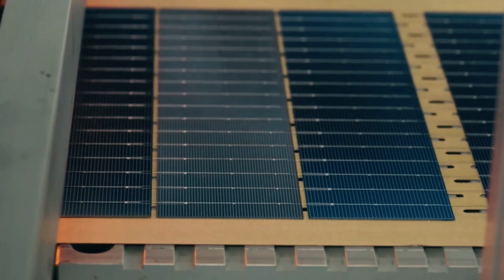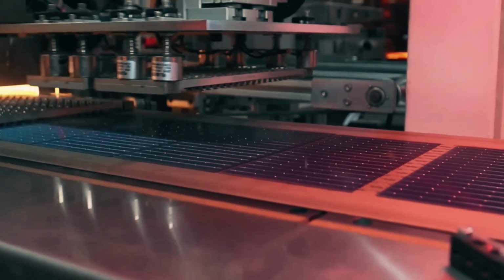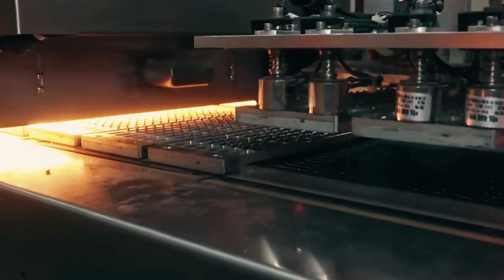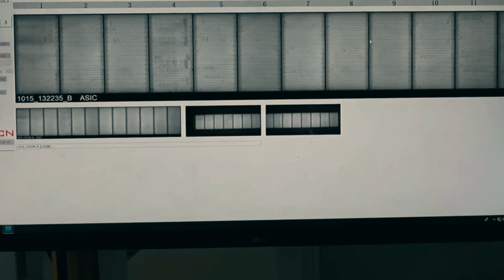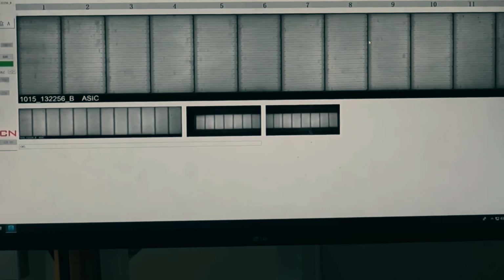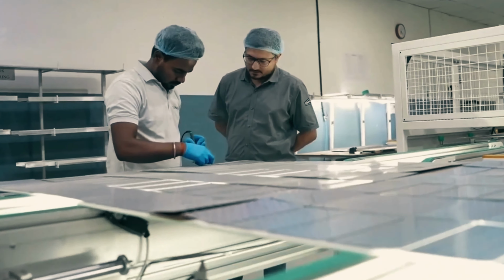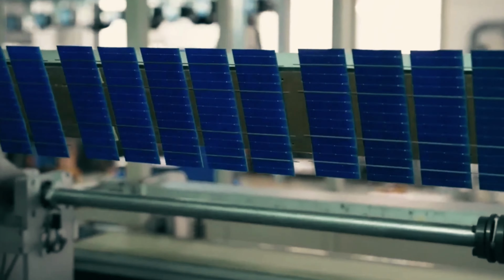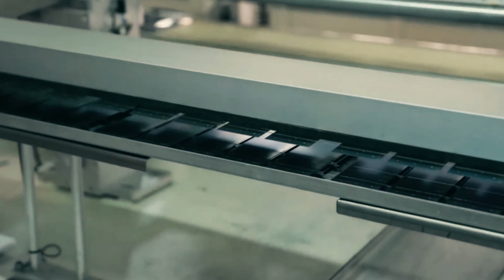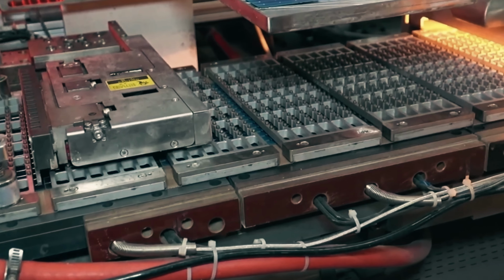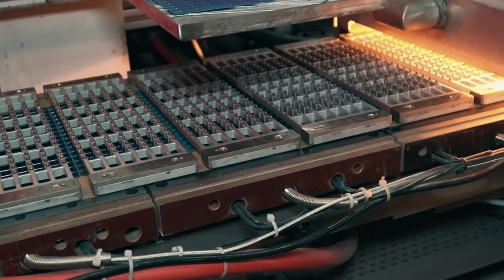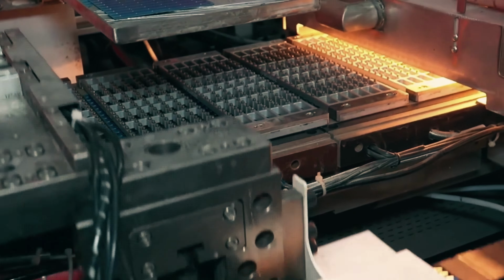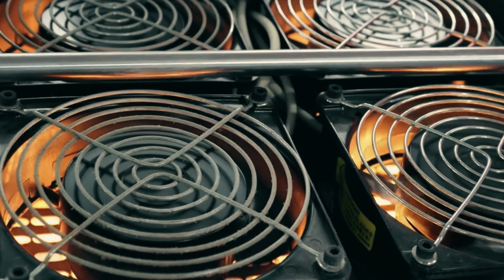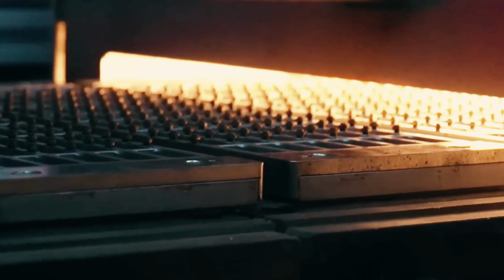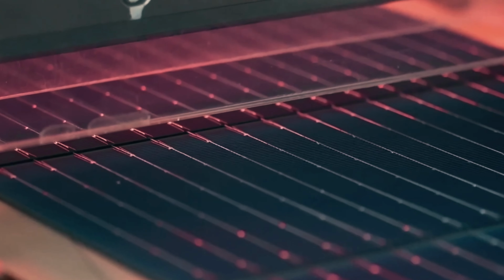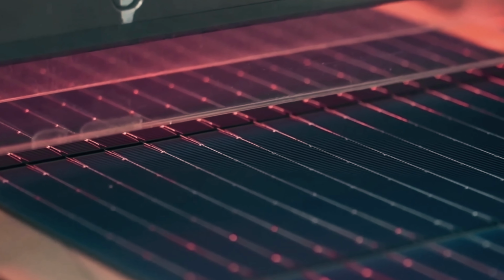Before it ever ships, every single panel is tested under a machine that simulates full sunlight for a fraction of a second, measuring its exact power output and flagging any cell with a hidden defect. A single trapped air bubble during lamination, invisible from the outside, can create a hot spot that slowly degrades the panel from the inside over years, which is why that vacuum sealing step is one of the most tightly monitored in the entire factory. But testing doesn't stop at that single flash of simulated sunlight.